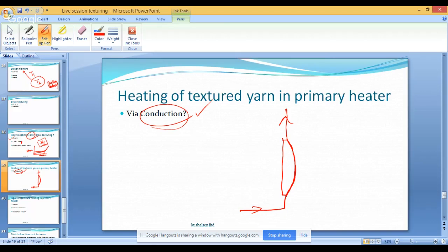And so what it would mean is that maybe part of the yarn is obviously in contact with the heater, but the air which is also swirling along with the twisting of the yarn would also be rotating around the same point, and therefore possibly the air is first going to be heated, and then that heated air is going to be heating the yarn. So what people have found is, although our intention was that the heating should take place by conduction, after all those calculations which did not support this conduction mechanism, a good amount of heating takes place through convection.